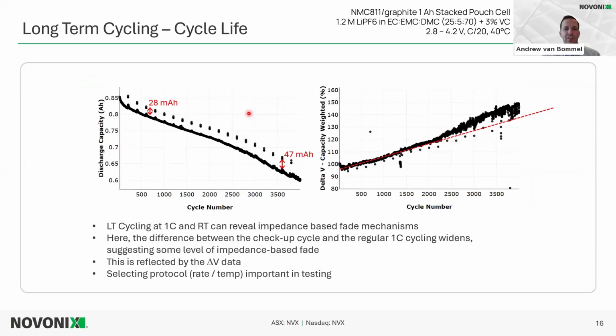So let's take a look at that. So this cycling is done at 1C rate at 25 degrees. So we get more cycles this way, but 1,000 cycles here can't necessarily be compared to 1,000 cycles at C/3, especially if it's time-based degradation within the cycling.